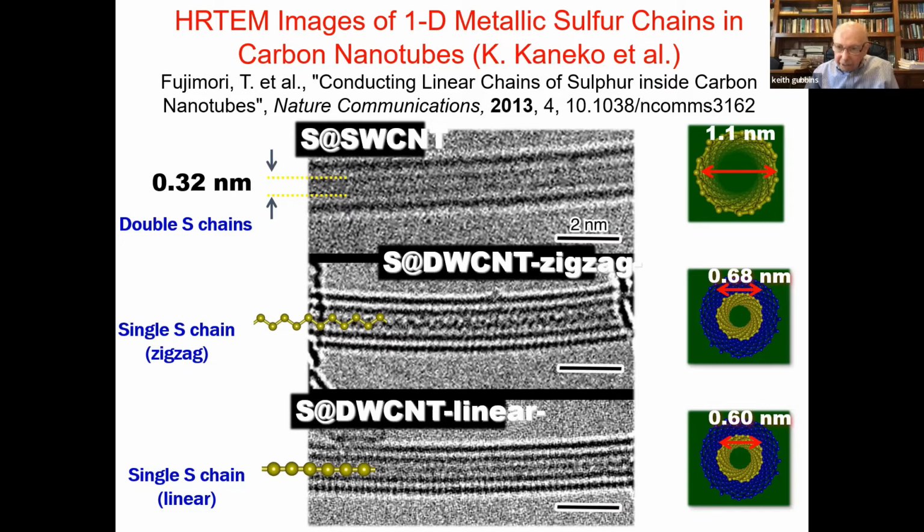And then if you go down to 6 angstrom units, this smallest chain, you see this linear chain, which is now a straight chain. There's not enough space for it to form the zigzag chain. And so they do other experiments on this thing, and they find the structure, and they find the sulfur bonding distance. So these sulfur atoms have reacted to form a polymer, and it's covalently bonded together. The bond length is about 2 angstrom units.